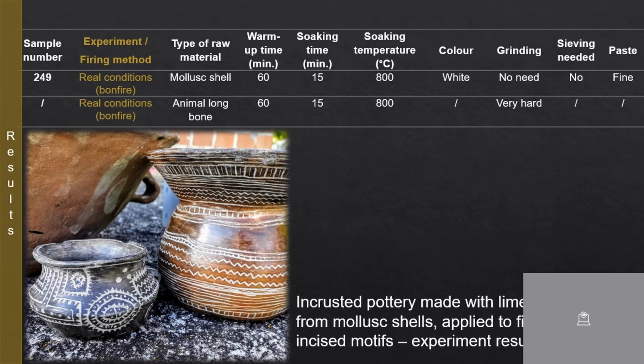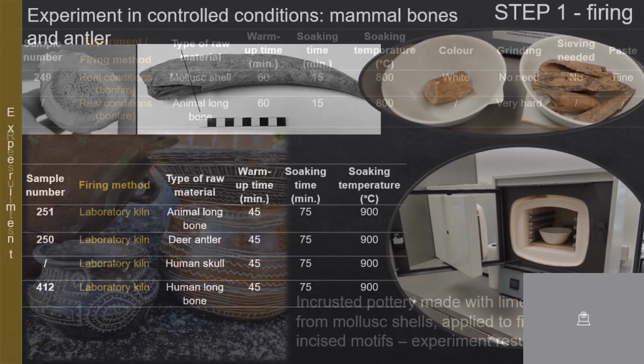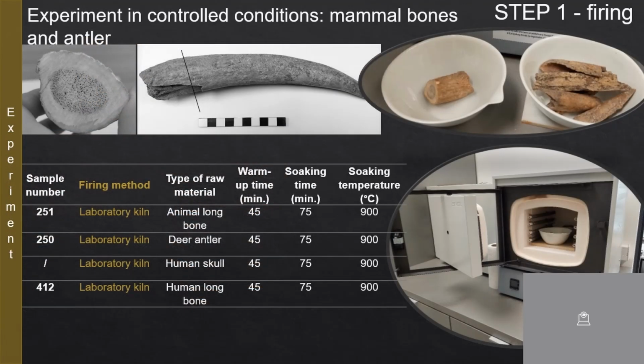In contrast, during the same experiment in real condition, the animal bone firing was unsuccessful. The bones did not calcify because of the short exposure to high temperatures. Therefore, we had to test bone material in more controlled conditions. We increased firing time, soaking duration, and temperature in a controlled setting and used different kinds of bone material.